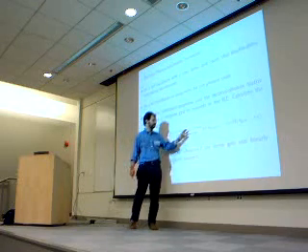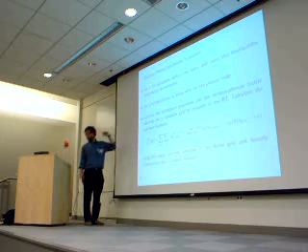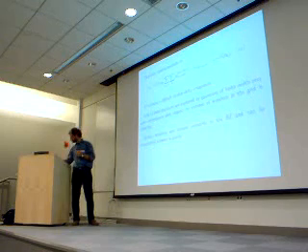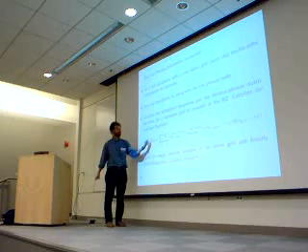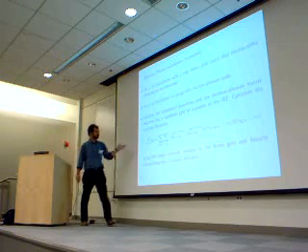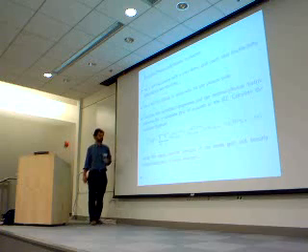So you move, let's say, one atom S in direction alpha, and then you consider the coupling with the displacement of an atom S prime in direction beta. If you do like that, then the previous quantity can be obtained simply by multiplying on the right and on the left, for any given eigenmode, by u alpha s and u beta s prime, and summing over alpha s and beta s prime.